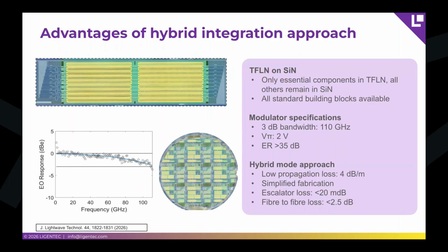The advantages of this hybrid integration approach is that only the essential components in thin film lithium niobate are used, meaning the modulation part. All other components remain in silicon nitride, where all the standard building blocks from the PDK of silicon nitride are available. The modulation specifications can go beyond 110 gigahertz with Vπ in the range of 2 volt and extinction ratios beyond 35 dB.